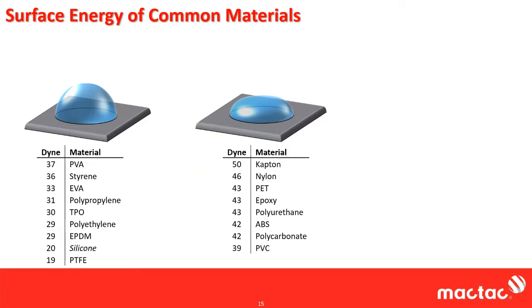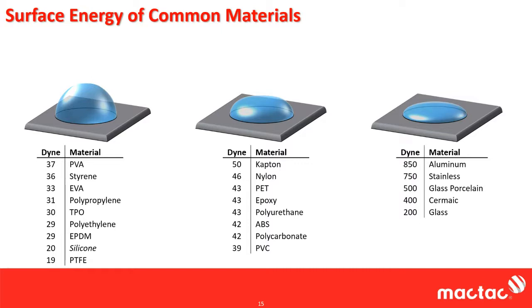Moving over here, we have what we call the high surface energy plastics, quite a bit higher than the low surface energy materials. Kapton, nylon, polyester, epoxies, polyurethanes, ABS, polycarbonate, and vinyl at the end there. All these are materials that are usually not known as hard to stick to. The materials on the far left, everybody has problems sticking to: polyethylene, polypropylene. These materials here are not very hard to stick to. Though we call these the high surface energy plastics, really it's about medium surface energy, especially when compared to the metals. As you see on the far right, we have the metals: aluminum, stainless steel, glass, porcelain. If you ever put a drop of water on them versus a plastic, the water just immediately wets out. It's very hard to see a drop. Again, it's because of the high surface energy.